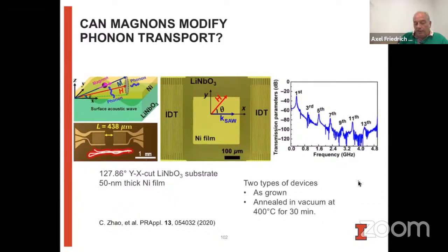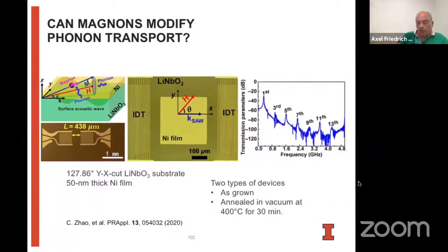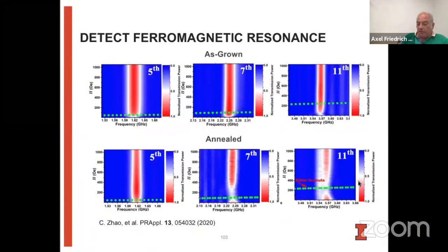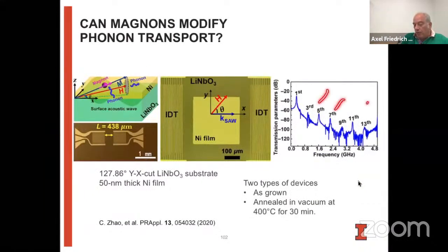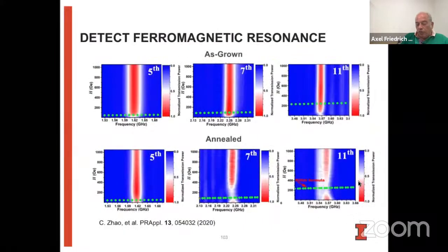We have these two interdigitated transducers, which are used for exciting and measuring these surface acoustic waves. In our device, we can look up to like the 11th, 13th harmonics. So we looked at two devices, one where the nickel was just as grown, another one where we annealed it afterwards to get better interfacial contact. As you go to different harmonics, essentially you measure at different frequencies. If you look at different transmissions of the surface acoustic waves, we see in the annealed sample clear dips in the transmission, so the surface acoustic waves are absorbed by the magnons, while in the as-grown device, there's much less indication that anything is happening there.